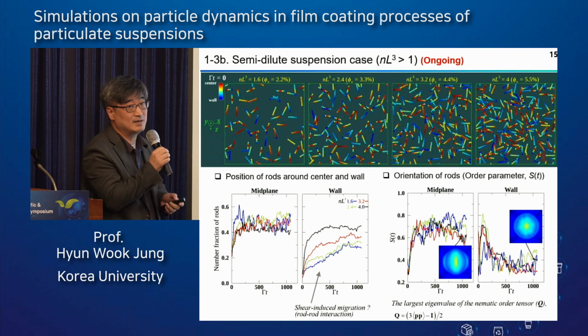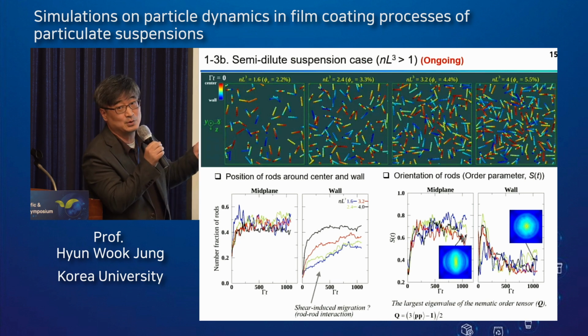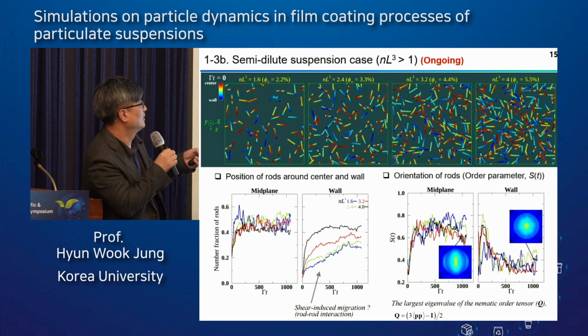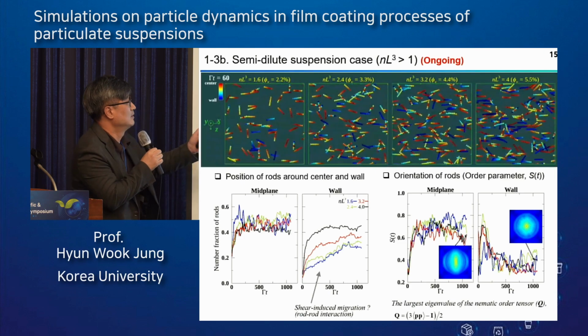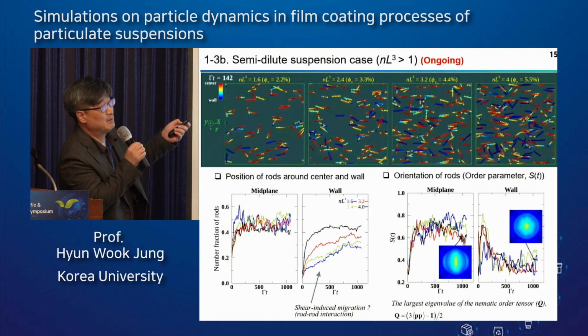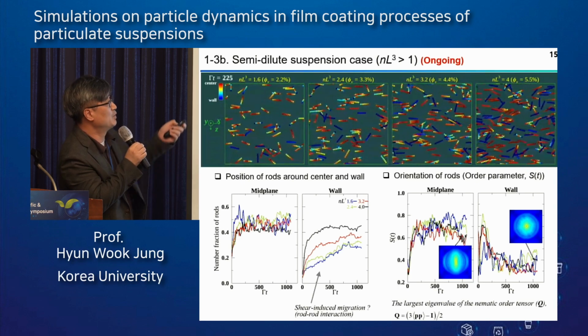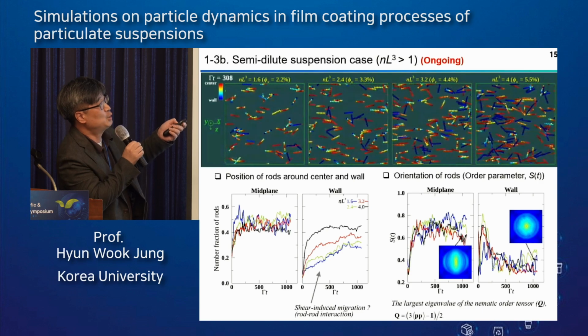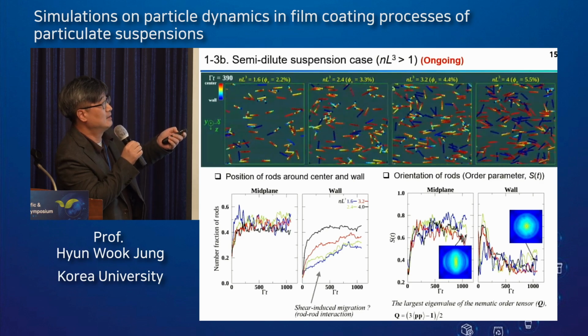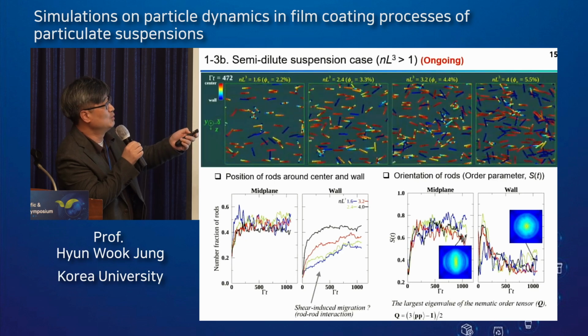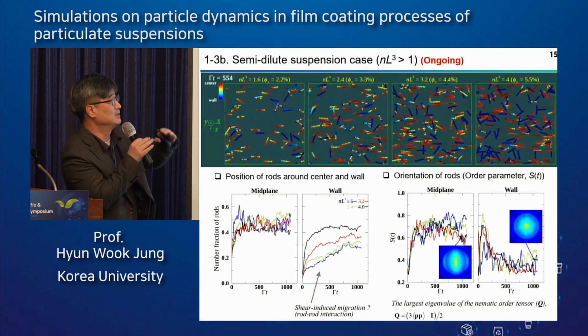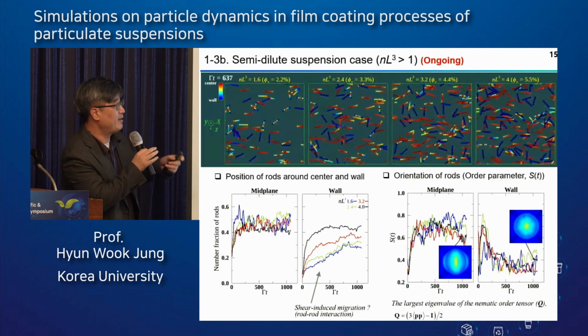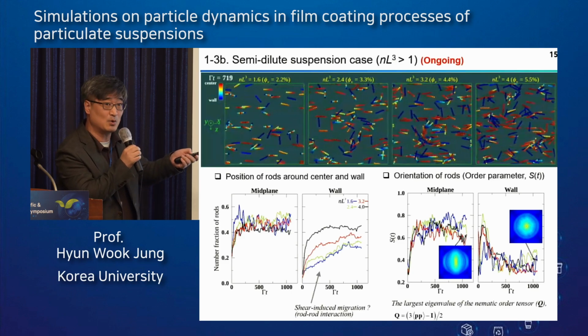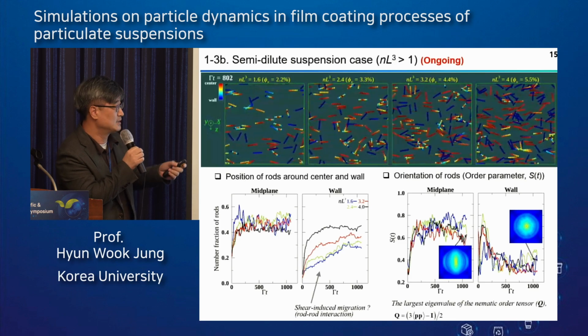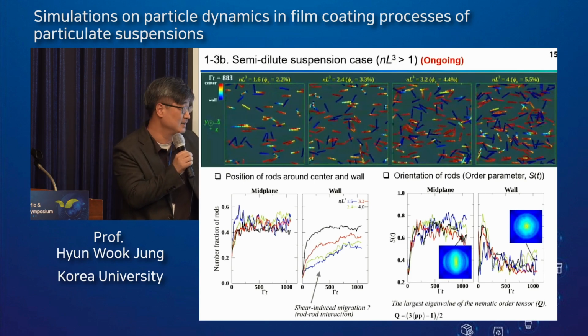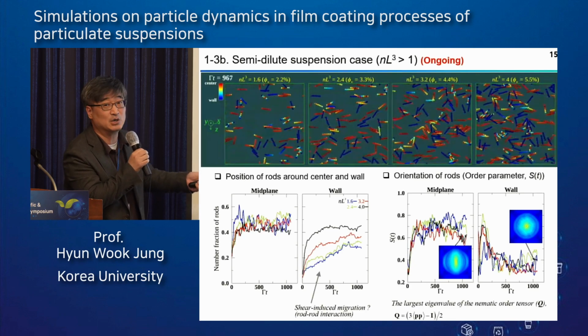And also, we increased the particle concentration to the semi-dilute regime, as shown here. So you can see some worm-like particles moving in the very confined channel region. So we increased the particle concentration. You can see two different colloidal rods: the blue colored ones moving toward the wall, and the other colloidal rods moving near the middle region. So we compared the transient position and orientation of colloidal rods around the center and the wall. As the concentration increases, the number of colloidal rods increases near the wall, as shown here.